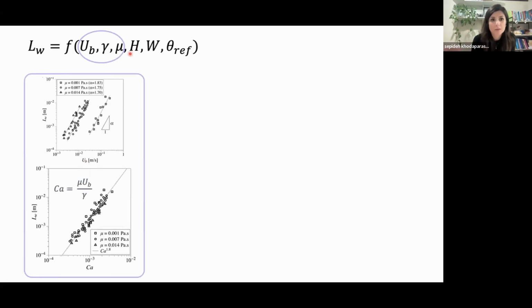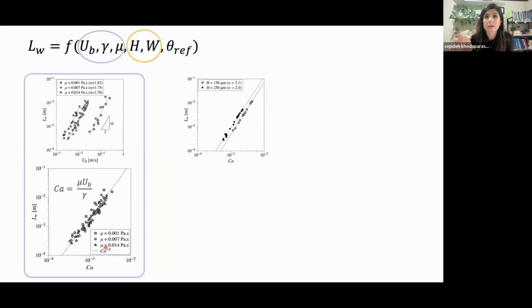If I now use the typical dimensionless capillary number, you see that all of the curves collapse onto one single curve. And the capillary number, again, is just the viscous terms over the interfacial term. I'm changing the viscosity of the fluid and the interfacial tension of the fluids in all of these, so they all collapse into one curve, which is what you expect from the other classic problem. What about the dimensions of the channel? Because there we had only the diameter of the tube. Now we have a rectangular channel. If I look at two different heights of the channel, obviously I get again a shift in the length from the nose of the bubble that's wetted.